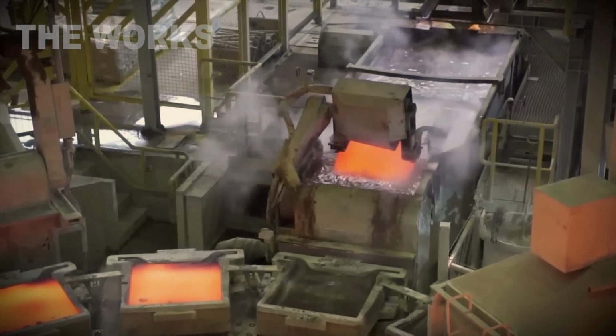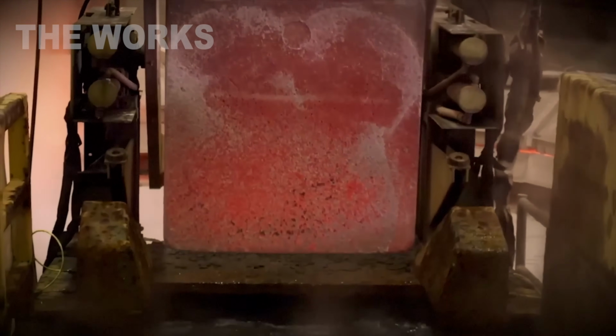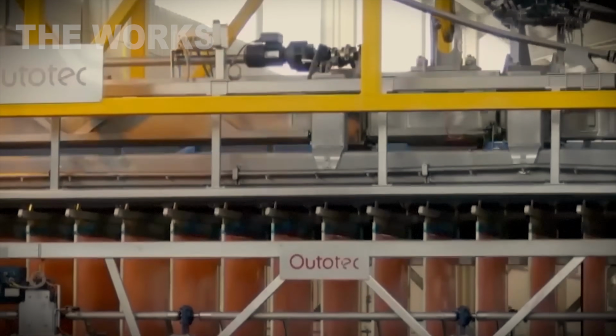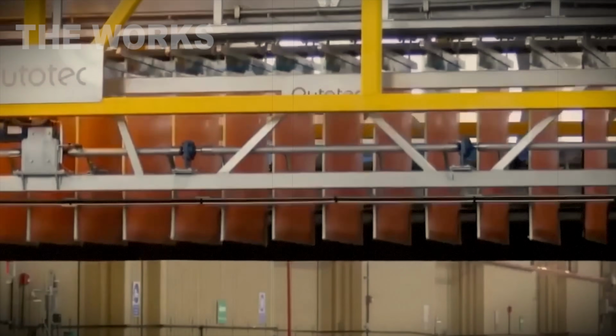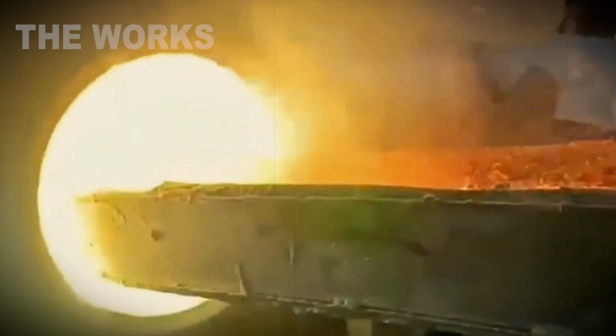Oxygen gets blown into the converter with the molten matte. A second oxidation happens. Sulfur burns off. Iron oxidizes and shifts into slag. What's left is blister copper, 98.5% pure. But we're not done yet.